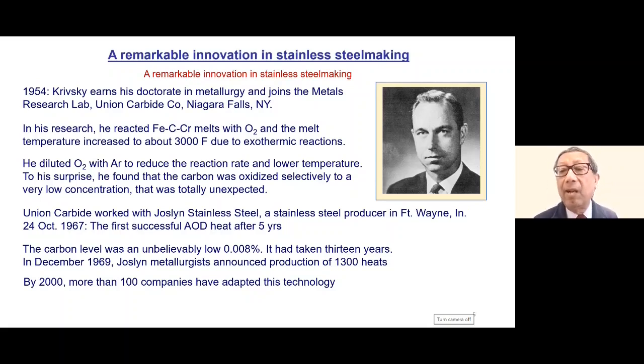He did a couple of those experiments, and to his surprise, he found that the carbon content was very low, lower than 0.01 weight%. And the temperature was lower, but chromium was not oxidized. So he thought that he had found a key for selective oxidation of carbon in an iron-carbon-chromium melt.